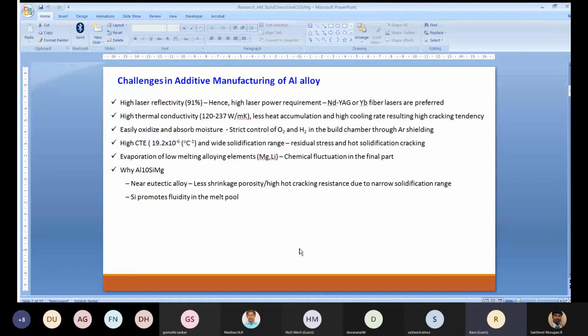Why we chose aluminium 10SiMg: because it is the workhorse in aluminium alloys, easily printable, process parameters were stabilized for it, and good success was achieved. Technically, it is a near eutectic alloy, so the solidification range is very narrow. So the problem of solidification shrinkage porosity or cracking is low. Second, the presence of silicon improves the fluidity of the molten pool, so you will not have problems related to fluidity.